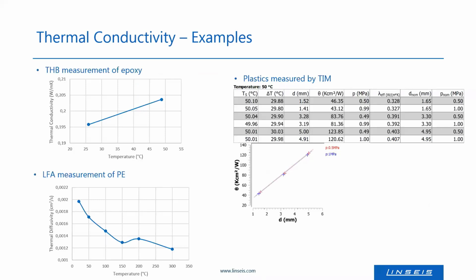And on this slide, you can see some examples of polymer measurements done by the just mentioned instruments. So for example, here an epoxy was measured in dependence on temperature using the THB. Here you see an LFA measurement of PE, where one also measures up to the liquid state. On the right, you see a plastic, which was measured by a TIM tester under several pressures, so 0.5 and 1 megapascal. And by that, one can, for example, investigate if the properties change under variable load. And here you see all of the results which were done for 3 different thicknesses of the material.